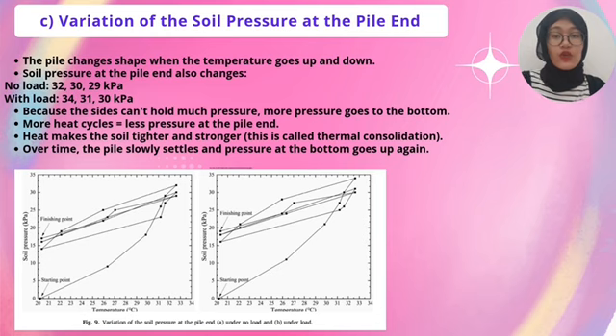Also, after going through more heating cycles, the soil has less pressure at the bottom. This is because heat causes thermal consolidation, where the soil gets tighter and more compact over time. But then, something interesting happened. As the pile settles slowly, the bottom pressure starts to rise again. The two graphs at the bottom show this clearly. The left one shows data with no load, and the right one shows data under load. You can see how soil pressure changes with temperature, from the starting point to the finishing point.